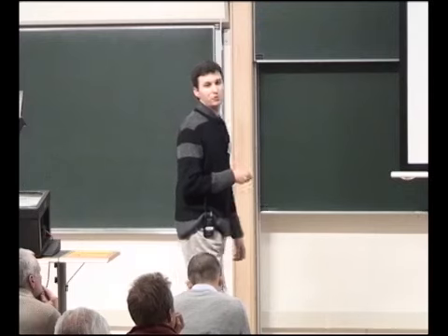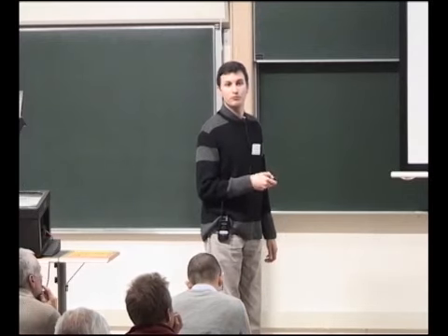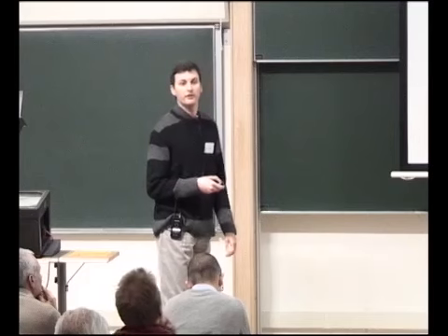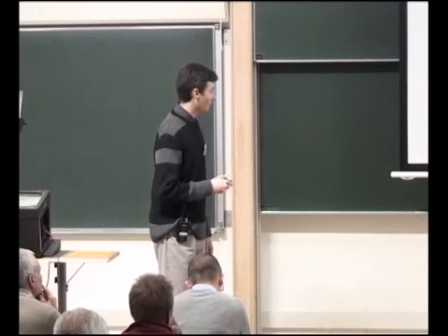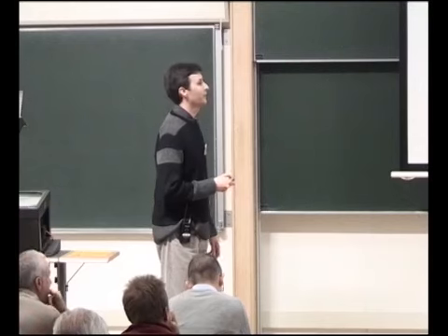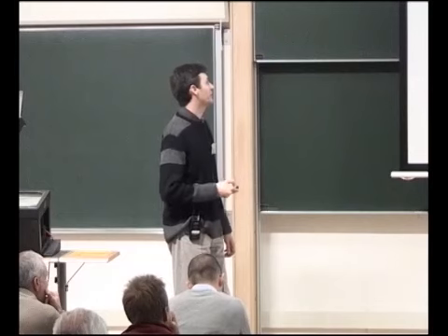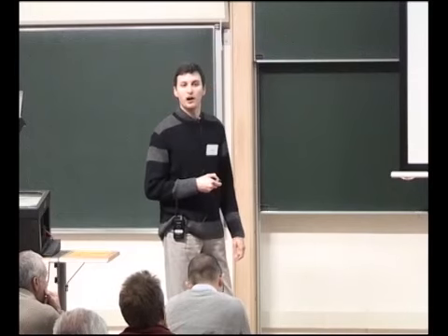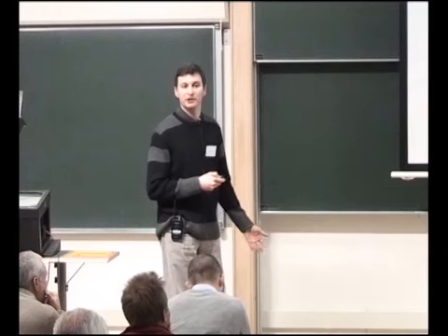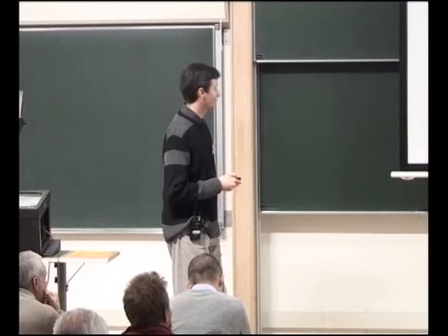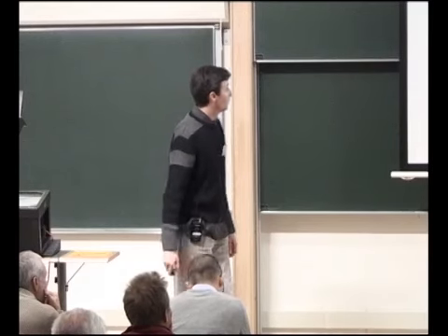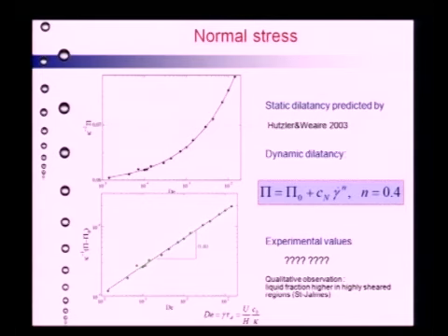Then we changed the exponent for the local repulsive force. It doesn't change anything. And the local friction force also doesn't change anything. So whether you take 1/2 or 2/3 like you should do, or you take 1, it always gives 0.5 something. So it proves that this value of the Herschel-Bulkley index is quite robust. It doesn't depend on anything. But then we don't understand anymore why Denkov observed that the rheology depends on the surfactant properties.